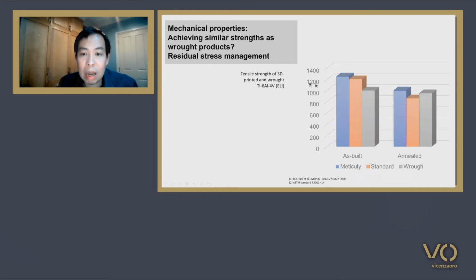In our work, we were able to accomplish the as-built strength beyond the standards, and even with annealing and microstructure treatments, we could still be above the standards for our printed parts. And this is how we do it.